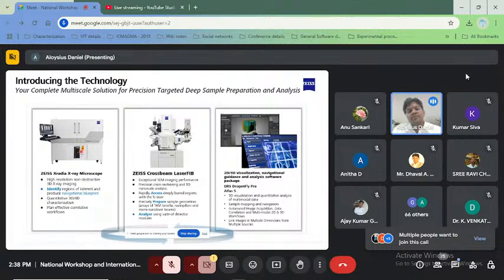Once the region of interest is selected, it could be one or multiple within the sample. The sample is moved from the X-ray microscope to a focused ion beam integrated electron microscope, where we also have the attachment of a laser beam as well. So the laser beam is used for removing bulk material, so that whichever region that has been identified using the non-destructive technique, now we remove the material and expose that region using the laser, and then you can use the ion beam to prepare the samples.